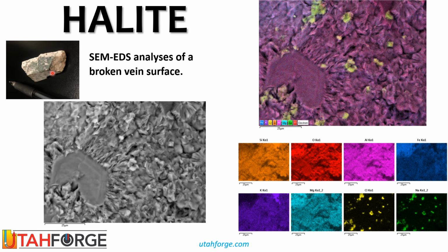So from the same photomicrographs as the last slide, a piece of the core was broken off. This is its rough surface, stuck under the SEM, and this is an image of that fractured rough surface. What you see here is part of a hexagonal clay mineral on its side. They're kind of shaped like plates. And this furry stuff are those same clay minerals on end. And then there are some lighter features in here. This cubic one is a good example.